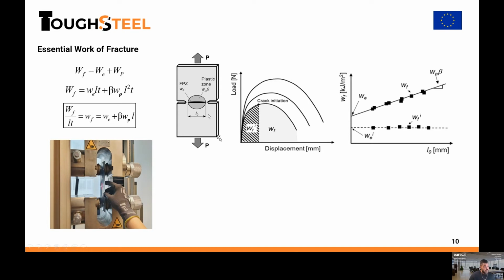Then, in summary, we test these specimens with different ligament lengths, plotting the load versus displacement curve and integrating the area under this curve, we obtain the total work of fracture. As we can see here, for increasing ligament length, of course, this total work of fracture increases. The energy for fracture is larger. Then dividing this work of fracture by the cross section, we convert this to specific work of fracture values, and we plot it as a function of the initial ligament length. We obtain a plot like this, and then we can separate both the essential work of fracture and the plastic work by making this linear regression. The independent term, in the intercept, is the specific essential work of fracture, and the slope indicates the plastic work.